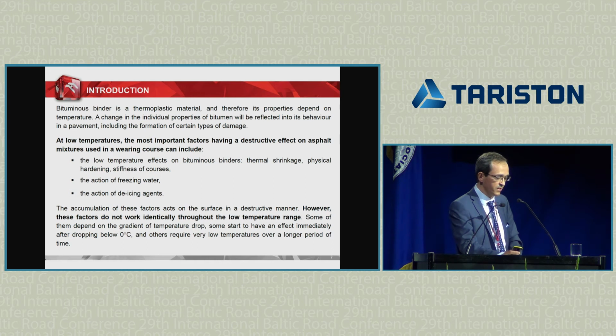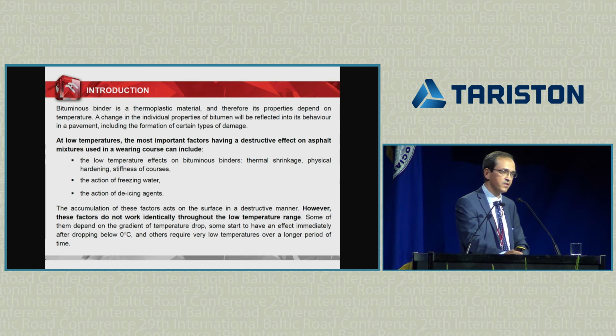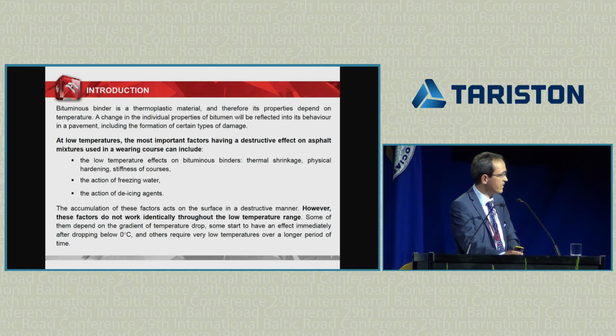At low temperatures, the most important factors having a destructive effect on asphalt mixtures, used especially in wearing courses, can include thermal shrinkage of the binder and asphalt mix, physical hardening, stiffness or over-stiffness of the courses, action of freezing water, or action of de-icing agents.